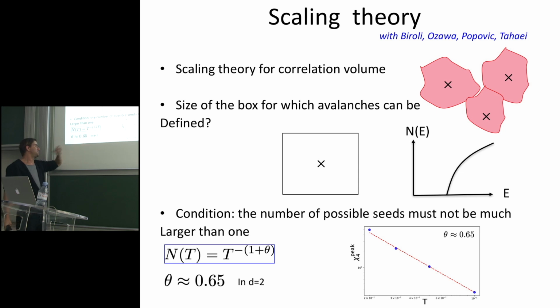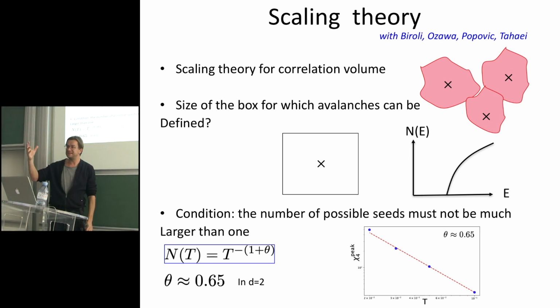We can measure theta to be 0.65. It's not too far from the mean field value 0.5. This is a theoretical prediction. And in those models, from the dynamics, from those movies I showed you, we can also measure this characteristic number of particles that are involved in the correlation at finite temperature. Okay, so we can also measure that. And this is called chi4, but essentially think of it as a correlated volume of the dynamics, and the theory works well. So at least for this system, we think we have the essence of what's going on.